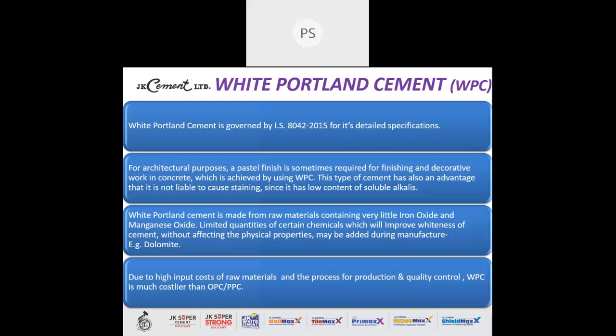Limited quantities of certain chemicals which will improve the whiteness of cement without affecting the physical properties may be added during the manufacture. For example, dolomite is also added by some companies. Fourth point, due to its high input cost of raw material and the process for production and the quality control, white Portland cement is much costlier than ordinary Portland cement or Portland pozzolana cement. While OPC or PPC you can buy at about 6 to 7 rupees a kg, white Portland cement you buy at a range of 40 to 45 rupees a kg. This is because of high input cost in the manufacturing and the raw material.